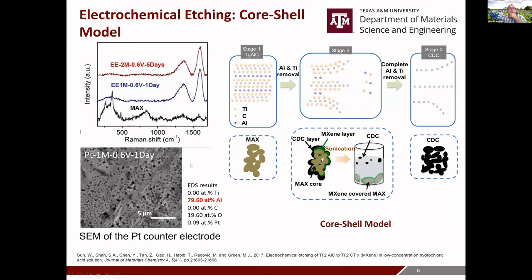So to explain all those results and what we are seeing, we propose a so-called core-shell model of etching in MXenes, where initially we first etch out the weakly bonded aluminum. But after some time of etching, titanium starts to etch out, leaving the CDC. And eventually, even with this porous electrode, when we crush it into powder, we can see the CDCs floating on the surface. What we end up with are mostly MAX phase particles covered with a slightly etched surface, as shown in